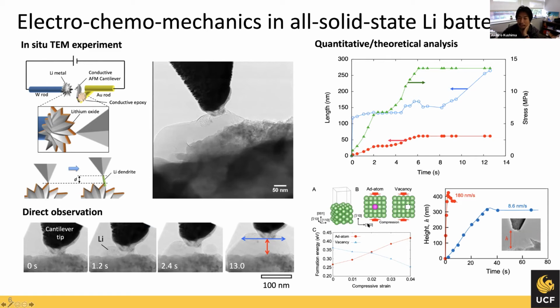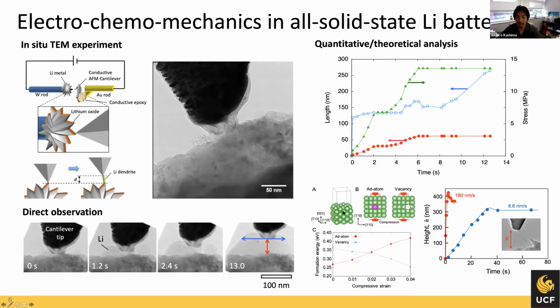And you can also combine it with a theoretical calculation. We found that by applying compressive stress at the lithium surface, it becomes easier to form a vacancy compared to the ad-atoms. So if there's a stress, there's a driving force to move the lithium away from the compressed area to the lower stress region. We've been doing this experiment for different conditions, and if you apply higher voltage and have a higher growth rate, there will be a larger force applied to this dendrite and also the electrolyte. Okay, so that's for the in-situ microscope.